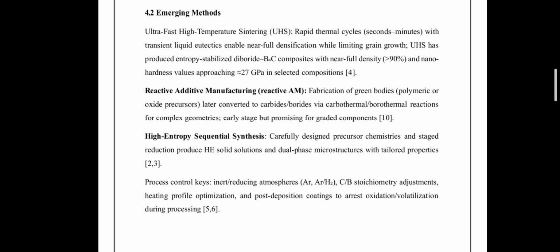These conditions promote the formation of transient eutectic or liquid phases, which dramatically enhance diffusion and allow near full densification while suppressing excessive grain growth. Recent studies demonstrate an entropy stabilized diboride composite processed by UHS achieving 90% relative density and nanohardness values approaching 27 GPa, highlighting its potential for advanced ultra high temperature ceramics.